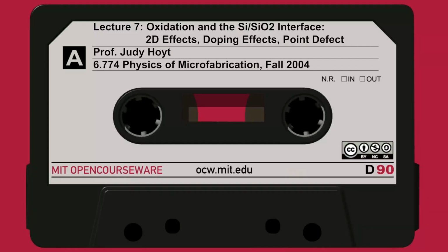It's important because it explains certain physical phenomena that are critical to fabrication, such as oxidation-enhanced diffusion, oxidation-retarded diffusion, and these things that tell us that the oxidation process itself dramatically changes the point defect distribution in the near surface region. And most of the ideas are related to the fact that there is volume expansion going on and the need for free volume at that interface. And so point defects play a role in that volume expansion.